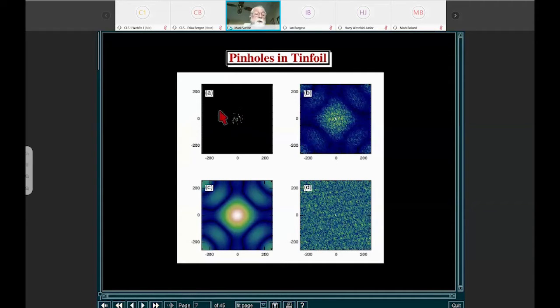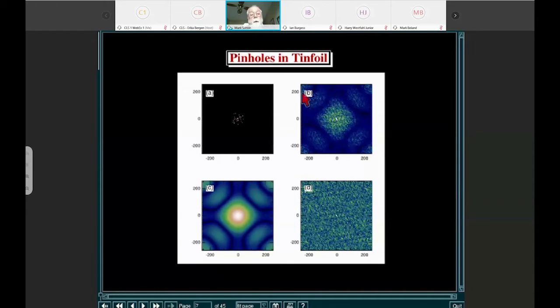So let's imagine we had a disordered set of scatterers. That's what's in panel A. There's actually a set of diamonds spread out randomly in some small area. If we simply Fourier transform that, and square it, we would see the diffraction pattern, which is what you see in panel B. And as a diffraction physicist, I would look at that and say, there are at least 2 important length scales in this system. One length scale is determined by the envelope of the scattering, which is given in panel C, and that is typically what we were measuring with X-ray diffraction. That scattering has a reciprocal space value of 2 pi over the size of the individual particles that are scattering.